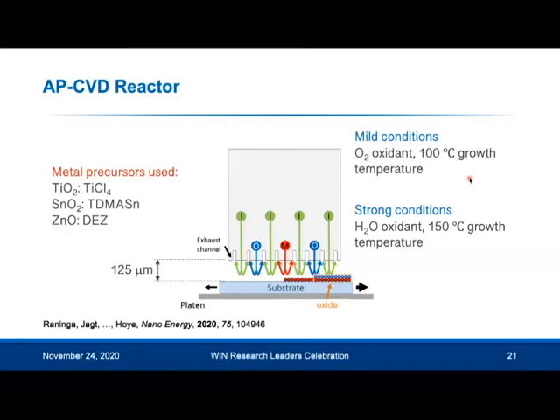And I'm comparing this against strong conditions, where I'm using water vapor, which is much more reactive with the perovskite, and a much higher deposition temperature, which is higher than the range of temperatures people have used in the past for the oxide buffer layer.